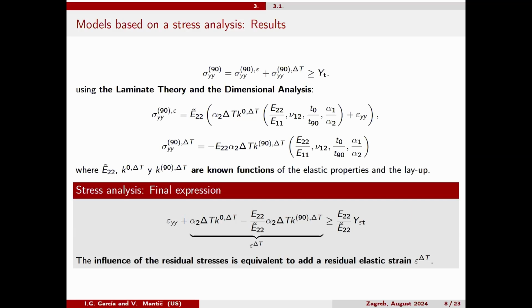So with that analysis, what we obtain is that the effect of the residual thermal stresses is just to add a term that can be calculated analytically to the mechanical strain that we are measuring in our machine, or we are applying in our structure. This is for the theories based on stress analysis.